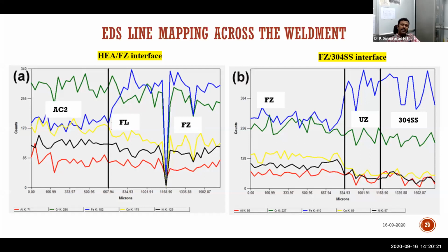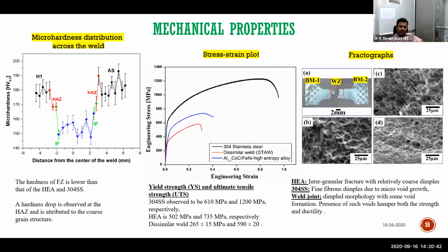Here also we are expecting at least decent weld efficiency, not like conventional weld systems, where even similar welding of aluminum alloys you will get 50 to 70% weld efficiency, whereas in dissimilar systems most of the occasions it is less than 50% weld efficiency. So based on this study background, we felt that we are supposed to get decent weld efficiency. So when we tested that, yes, we got a decent weld efficiency.